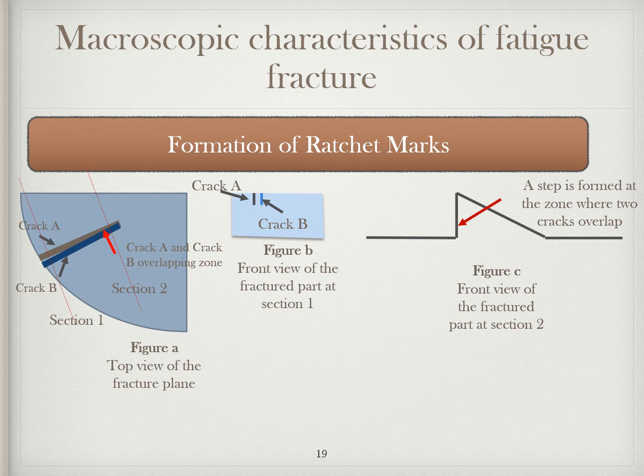When adjacent cracks overlap, the metal in the overlap area will then fracture across the short distance between the two cracks. This in-between fracturing creates a corner angle perpendicular to the surface of the part, as shown in figure C. So now let us see figure C. This is again the front view of the fractured surface, but it is taken at section 2. This section is taken at the overlap zone. At the overlap zone, we see a step being formed where the propagating cracks overlap. This is called the ratchet. It is perpendicular to the fractured surface.